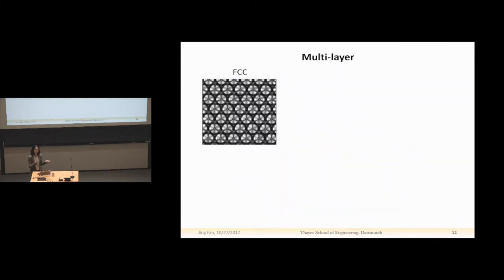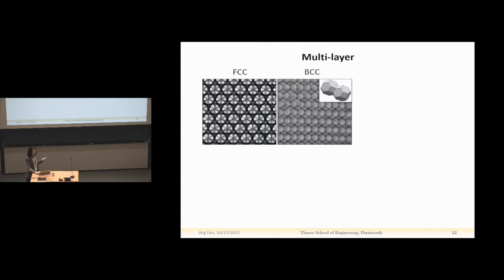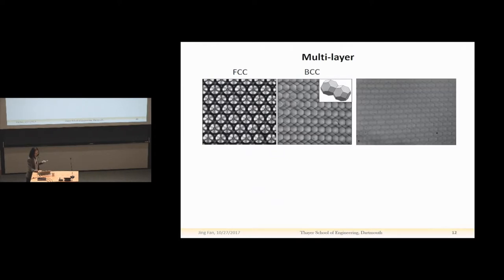And similarly, we can further increase the distance between the two plates. So we have multiple layers of drops packed in between. And in this case, at relatively low volume fraction of the drops, we have FCC packing structure. And when the drop volume fraction is higher, close to one, we have the BCC packing structure. And actually here I have a video showing seven layers of BCC packing structure from the first layer to the seventh layer. I adjust the focus of the microscope, but you couldn't even see the difference because they are perfectly packed in BCC. So every layer looks exactly the same.